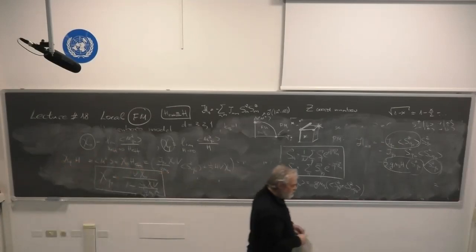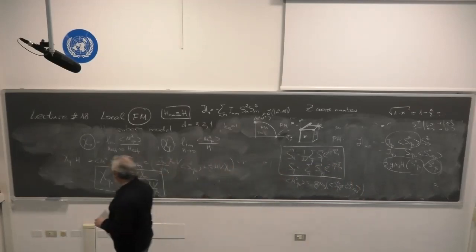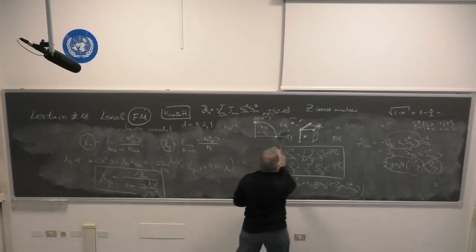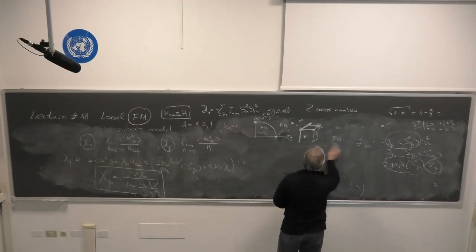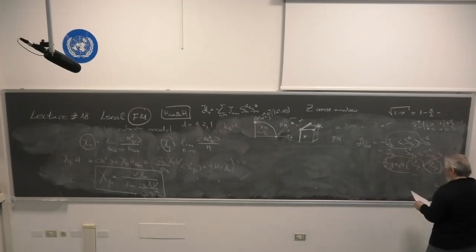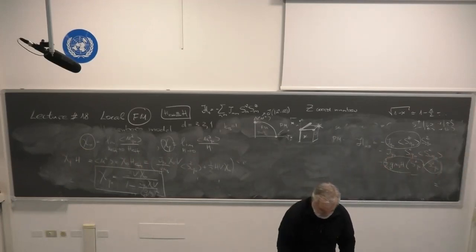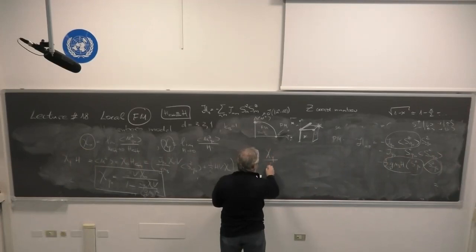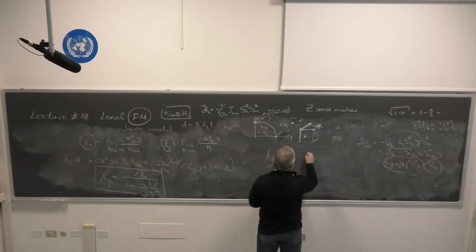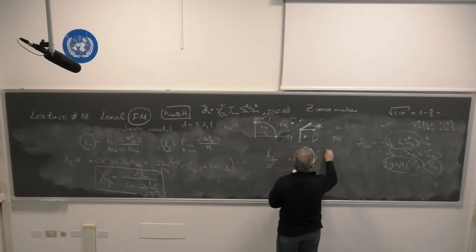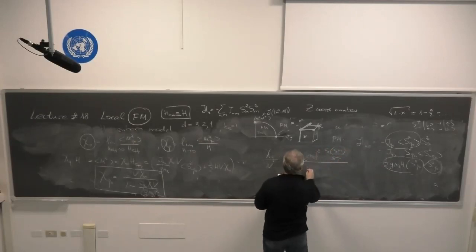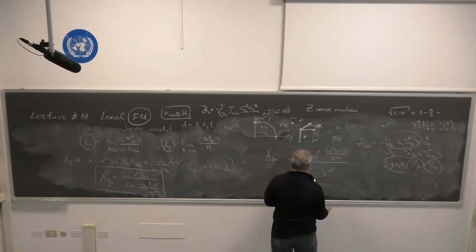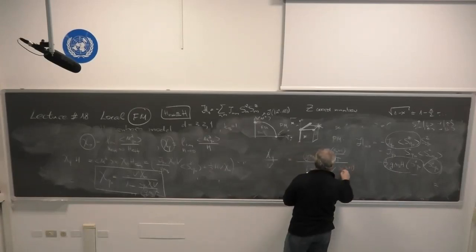Okay, now I'm saying that I selected a particular Q naught, but let me now replace Q naught by arbitrary Q. This is the spirit of the random phase approximation. This is what we did for Coulomb interaction. And I'm writing that chi_Q, if I divide by the number of spins, is equal to g mu_Bohr squared (S plus 1) over 3T divided by 1 minus J_Q times N times (S plus 1) over 3T.